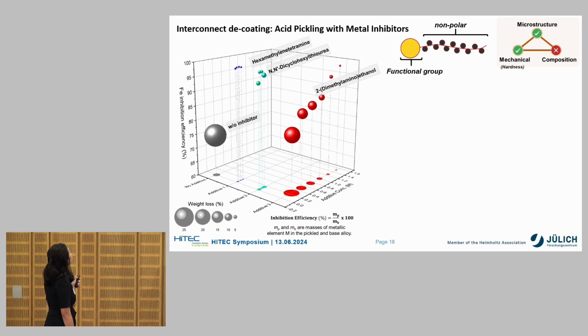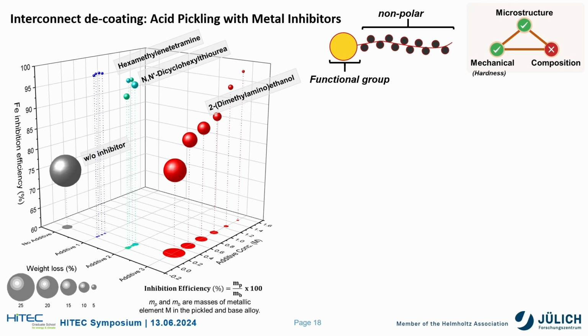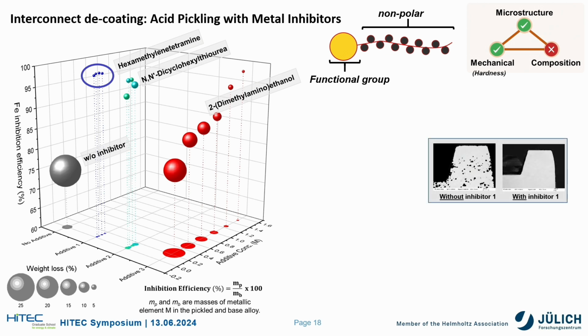So we tried 3 different metal inhibitors and assessed their alloy inhibition efficiency. In this graph, you see these bubbles, right? The smaller the bubble size and the higher it is located in the y-axis, the better it is in minimizing the dissolution of the base alloy. And based on these results, these blue additives called the hexamethylenetetramine are the best one, yielding the best inhibition efficiency for the alloy and effectively minimize the formation of the pores, as shown in this image here.